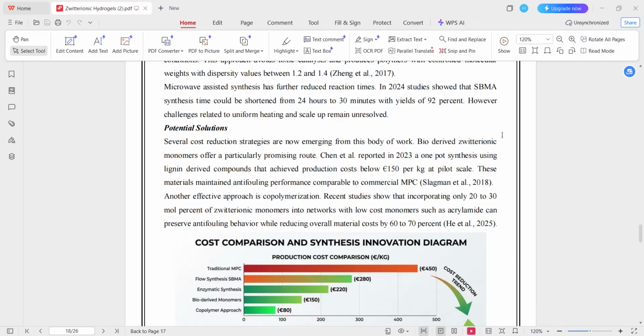Another highly effective approach is copolymerization. Studies show that incorporating only 20 to 30 mole percent of zwitterionic monomers into a network made from low-cost monomers such as acrylamide can preserve antifouling behavior while reducing the total material cost by 60 to 70%.